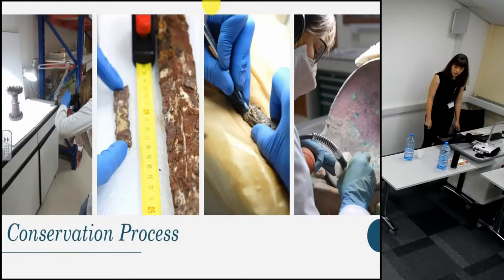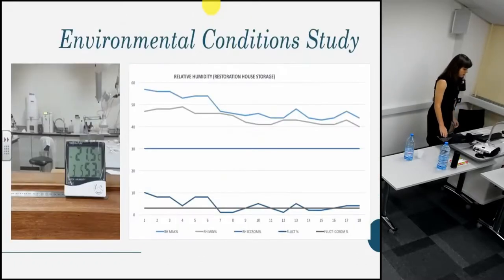I'll give a brief rundown of our treatment methodology. While most treatments generally follow this format, each object can present its own challenges which mean we need to adapt our approach. Each object is photographed prior to treatment along with measurements, drawings and condition diagrams. When possible we x-ray the object. The surfaces of metal artefacts are almost completely obscured by carbonates and corrosion products, which are removed with mechanical cleaning using scalpels and rotary tools, where possible under magnification.